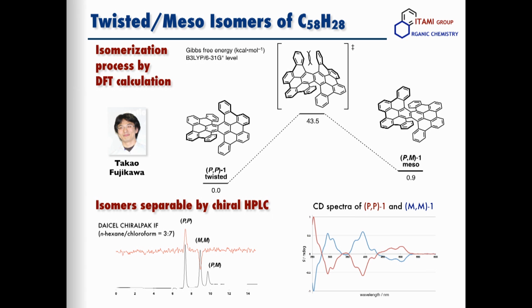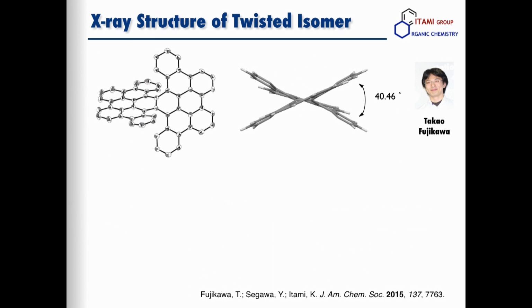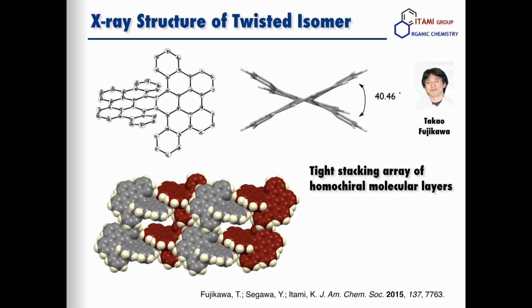We separated them, and indeed we took CD spectra, and as you can see here, these are really nice enantiomers. It's consistent with the theoretical calculation as well. And this is an X-ray crystal structure of the twisted isomer shown here. And this is the most exciting result. As you can see here, there are homochiral monolayers, and then they stack on each other.